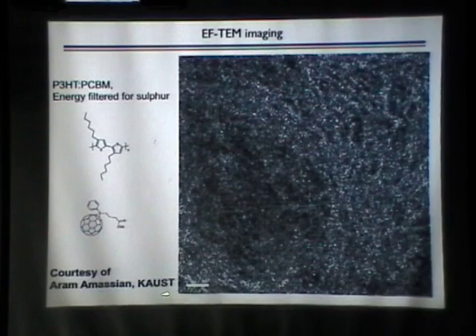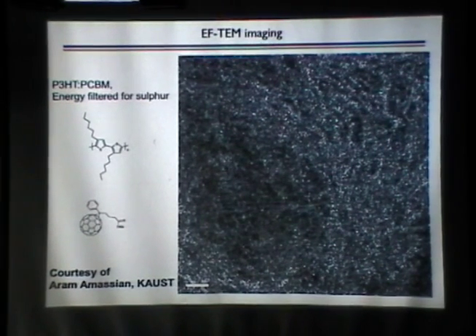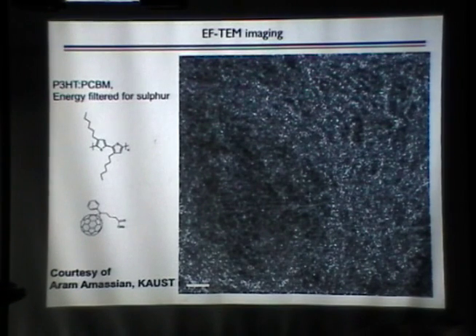I should mention that this work was done by a colleague at King Abdullah University of Science and Technology in Saudi Arabia. Another thing we can do is distinguish between these two molecules, and we can aim at that sulfur atom that's on the thiophene. So we can use energy filtered TEM to hone in on, or to focus in on, a given atomic species. So if we look at sulfur, we're basically looking at just the polymer. And what you see is a distribution of the polymer that forms some kind of periodic structure.